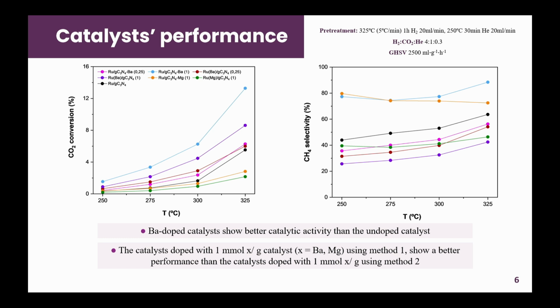So finally, the best catalytic activity performance was obtained with the catalyst doped with 1 millimole of barium using the first doping method. And as we have seen, that may be due to the incorporation of barium in the structure, leading to a higher ruthenium dispersion, a lower ruthenium support interaction, and the presence of more nitrogen defects.